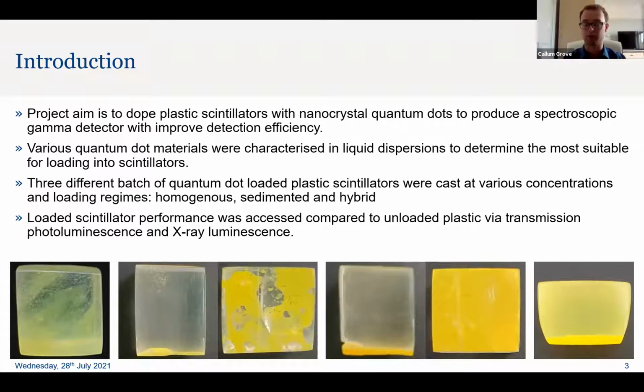We did an investigation of several different quantum dot materials in liquid dispersions, dispersed in toluene, and compared their emission and absorption characteristics to try and work out what the best properties were for loading into a plastic scintillator, and then selected the best. And we made 3 batches.